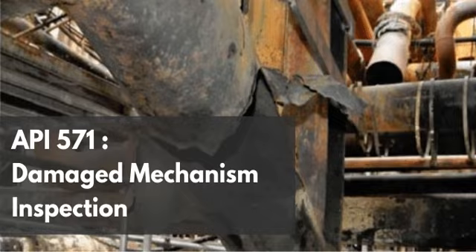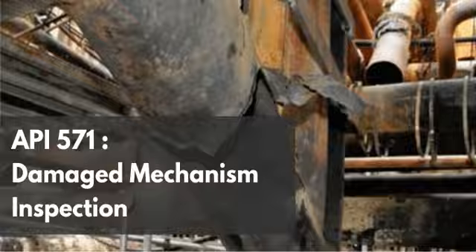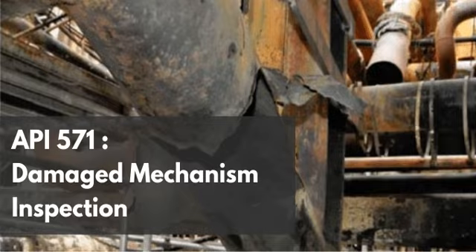Yes. But as that outer microscopic layer of the steel absorbs the carbon and forms all those dense metal carbides we talked about earlier, it reaches a state of matrix saturation. The sponge gets totally full. It literally cannot hold another drop. Precisely. The outer surface becomes completely saturated with carbon.